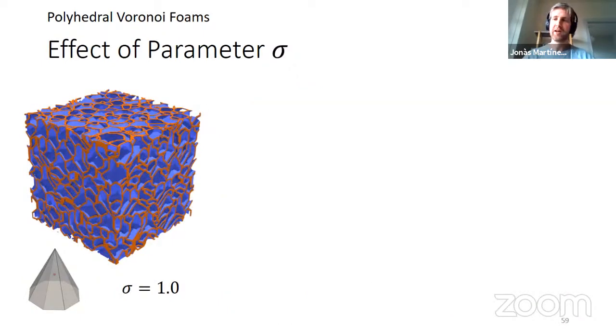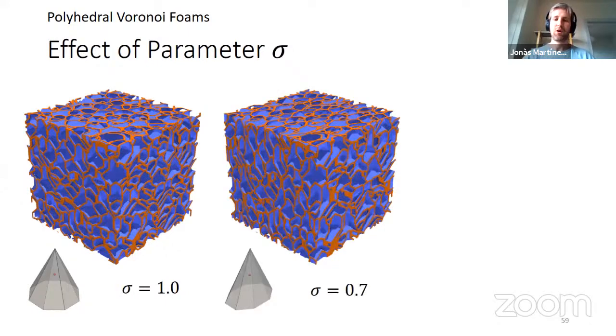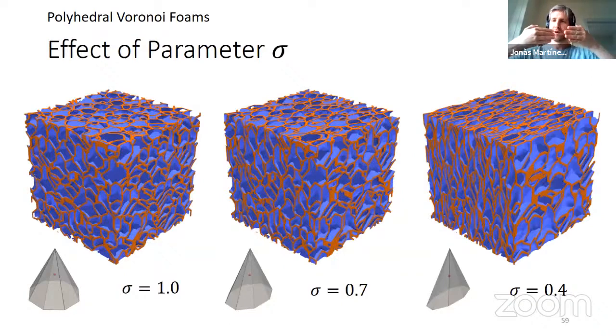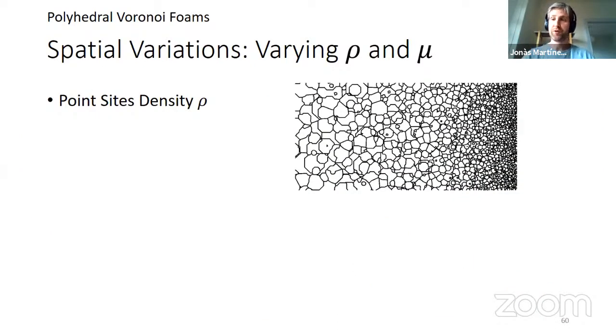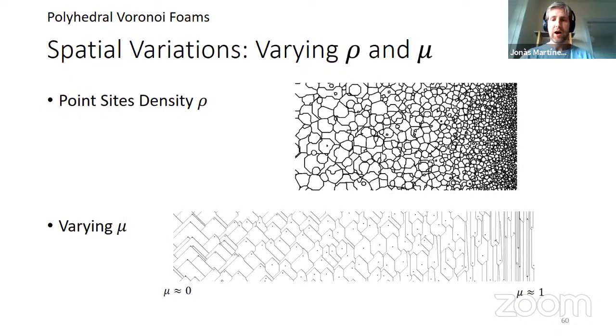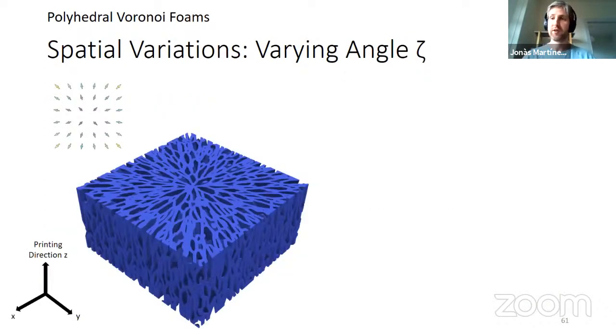The parameter sigma is basically a stretching that we do in one direction. And the more we stretch in one direction, the more the Voronoi faces get elongated in that direction. And then we expect to get some orthotropy, anisotropy, in that direction. And finally, that's the nice thing of procedural foams, that you can play intrinsically with the point seed density. So that's one slice. And you can also play continuously with these parameters. So here you can see how we continuously grade from mu0 to mu1, which is from no vertical walls to almost all vertical.